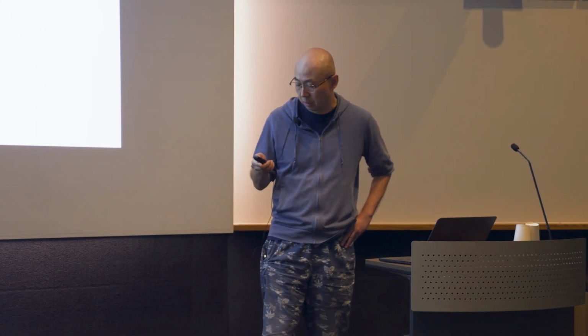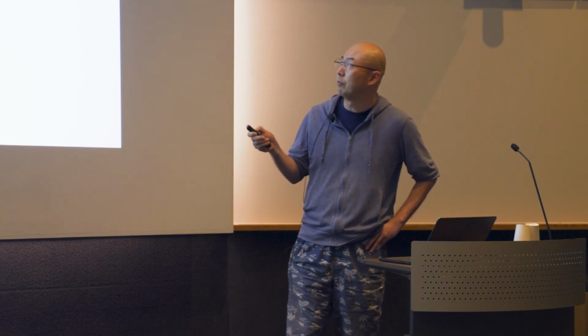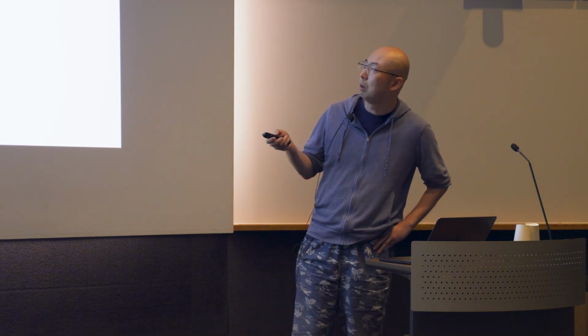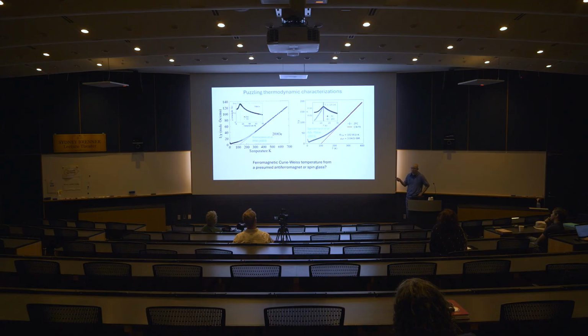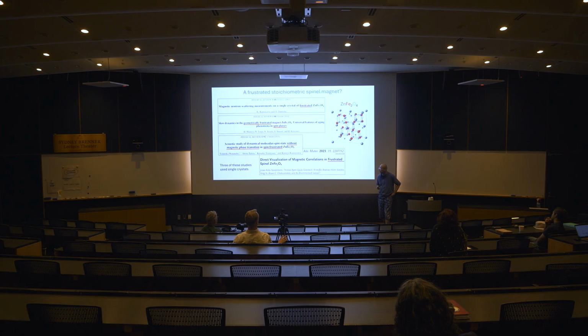But of course, the data has been consistent through the years, and that's the main puzzle. The fact is that the Curie-Weiss temperature of 100 Kelvin compared with the peak temperature of 13, the ratio between them is about 8. This is a very large number and typically regarded as a very strongly frustrated spin system.